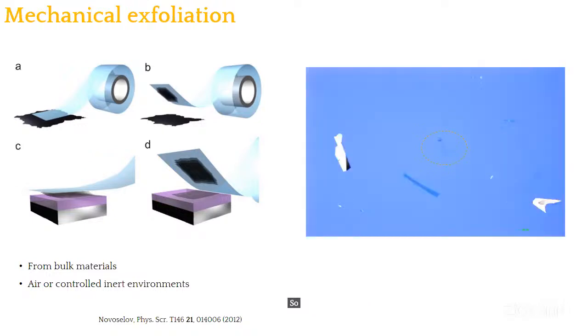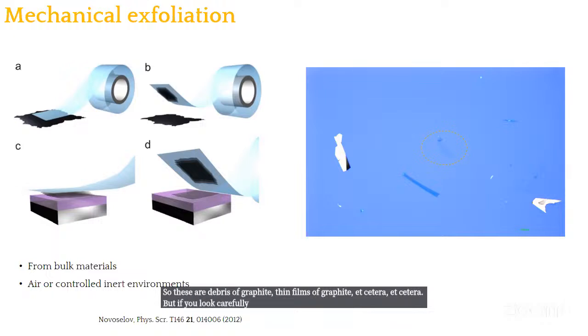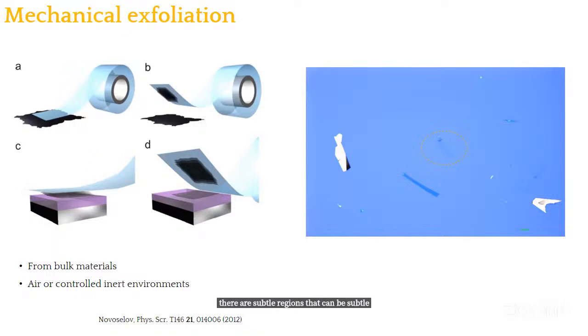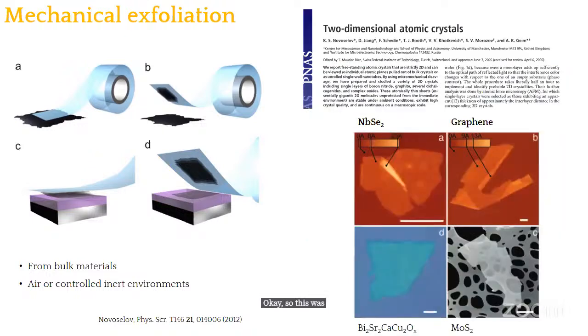Here I show you an optical image where you can see the debris. I think this is graphene or graphite. So these are debris of graphite, thin films of graphite, etc. But if you look carefully, there are subtle regions that can be potentially very thin, down to a monolayer. This was first done by Kostya Novoselov and Andre Geim back in 2004 for the first isolation of 2D materials. In particular, they did it for graphene, niobium diselenide, molybdenum disulfide, and other systems. Of course, you know that this was awarded the Nobel Prize in Physics.